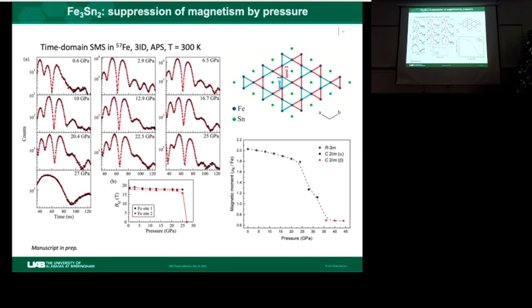You just need to assign these different hyperfine interactions, hyperfine magnetic fields, to different bond lengths, and we can sense very small variations coming from the iron-iron exchange interactions.